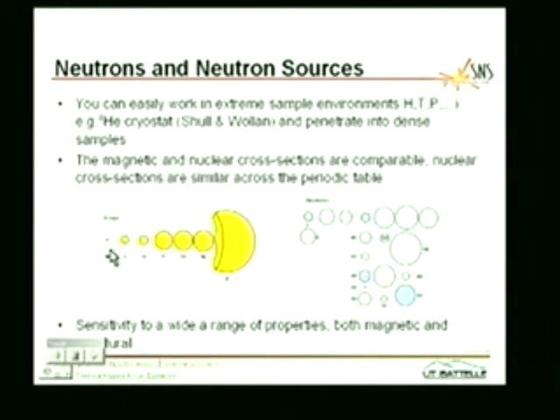No matter how intense your X-ray source is, there's a sort of fundamental signal-to-noise issue that you have to grapple with, just because iron, or even worse, uranium, has a lot more electrons than the hydrogen, which is just sitting there with one. In the case of neutrons, this shows the neutron cross-sections for the same elements, except now we